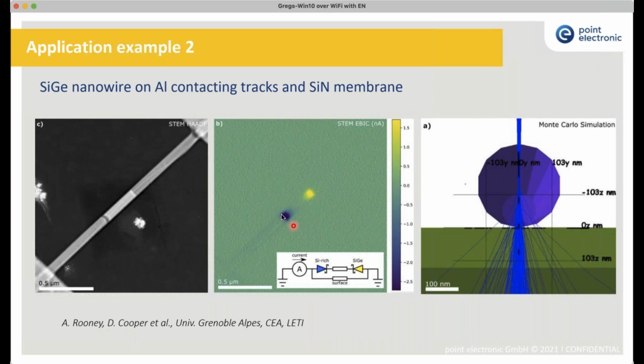It also shows us the shape of the field. So we see that the field is inside the silicon germanium nanowire, of course, cannot be inside the aluminium. And we also know it's opposite. We're collecting holes from one, electrons from the other, so we know they're back to back. So immediately we have a little circuit that we can model our experiment to.